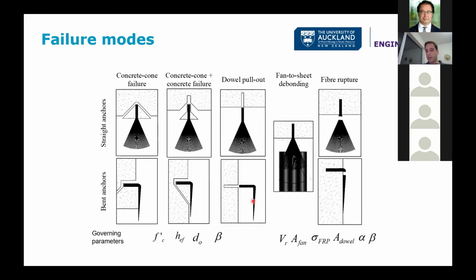But looking through the literature, I saw that there was a lot of research on this failure mode. And I thought, even though there is always space to do more research, it was pretty well researched. Then looking at the next failure mode, fan to sheet debonding, where the fan debonds from the sheet in the background, the parameters are the shear strength of the resin and the area of the fan. But I thought this was not really interesting to me, and not complex enough for a PhD project. So I focused on the fiber rupture failure mode, where all the fibers break, usually there in the key portion, whether we have straight or bent anchors.